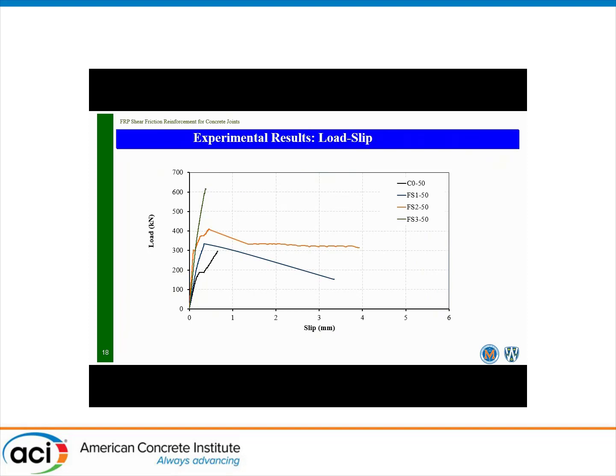In terms of test results, this diagram represents the behavior of an unreinforced plain concrete specimen of 50 megapascal. As you can see, it can be categorized into 2 bilinear stages: the first stage when only cohesion exists, and after the cohesion is destroyed between the concrete, then friction takes place up to a certain limit. With no reinforcement, after the limit of friction, the specimen failed suddenly without showing significant resistance.